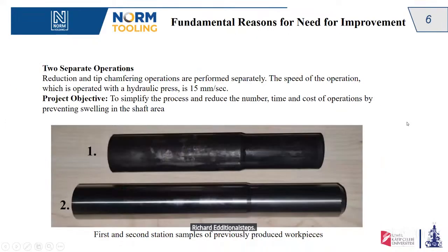The fundamental reason for our need for improvement stemmed from the existence of two separate operations. Reduction and chamfering operations were performed separately. The speed of this operation, carried out with a hydraulic press which is quite slow, was 15 mm per second. This situation extended the production time and reduced overall efficiency. Our project objective was to simplify the process and reduce the number, time, and cost of operations by preventing swelling in the shaft area. This is the shaft area. The parts numbered 1 and 2 in the slide represent first and second station samples of previously produced workpieces, illustrating what we faced before the improvement.